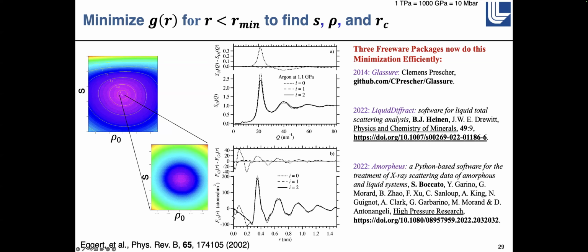So the first time you get f of R, you get these big variations at low R. When you do the analysis, it rapidly converges to this sort of straight line at the low R. And then you can try to get this line as straight as possible by optimizing the background subtraction and the density.